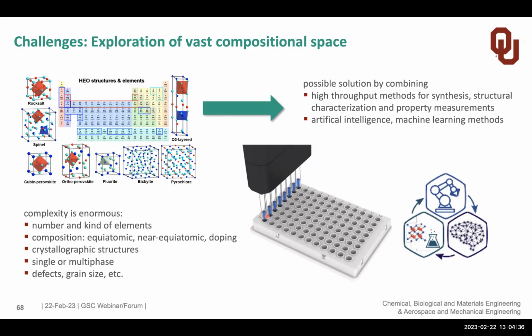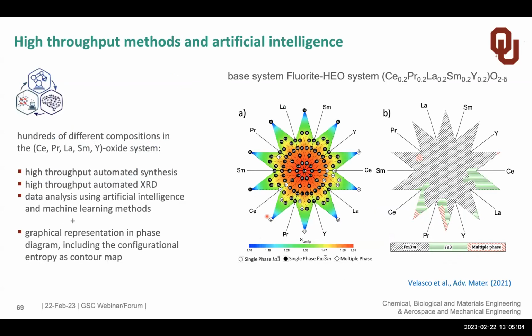And then we anneal it afterwards, make a high temperature treatment, and we convert the salt, which is typically a nitrate, into an oxide. And because in each of the pockets we can have a different composition, we can scan the compositional space rather quickly. But this also means we need the synthesis robot, and we need the characterization robot for structure, but also for the property. And we have done that for measuring hundreds of different compositions in this rare earth high entropy oxide system.